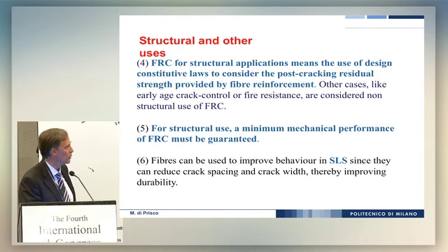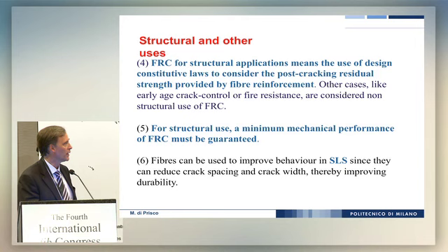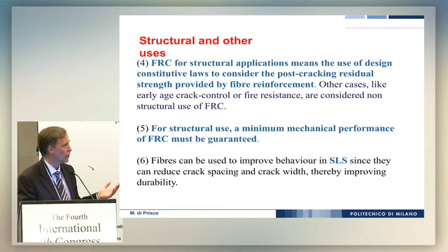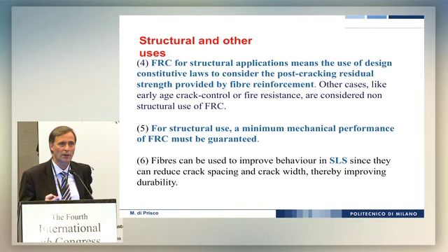About the use, we divided structural use from a use which is denominated non-structural, even if we can debate about the denomination. But we would like to emphasize that in some cases, when you have structural use, you use the constitutive laws, and so you put in the equations the contribution of fibers in terms of stress-crack opening. And in other cases, we have just the experience, so experimental data that highlight that the benefit is real, is very important, but we don't have enough experience to quantify this contribution with a constitutive law or mechanical approach. So we split the use in this way, but it's obvious that especially for the serviceability limit state, the second one, the non-structural use, is also very important. It's enough to think perhaps of polypropylene fiber for spalling, explosive spalling.